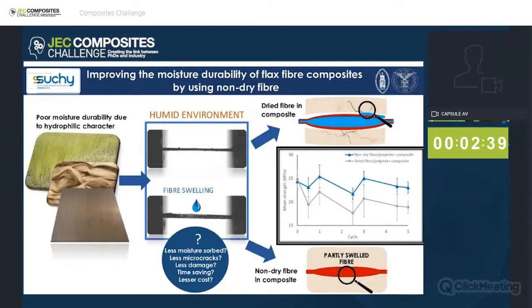additional advantages of using non-dry fiber could be lesser cost and time saving in the manufacturing of composites, since the process of oven drying the fiber is eliminated. So this simple idea inspired us to investigate the potential benefit of using non-dry fiber over the oven-dried fiber in composites. So in this research, we hypothesized that for composites made of non-dry fiber, which already contains some amount of moisture and is already partly swelled, the swelling and shrinking of the composite due to moisture absorption is reduced, thereby retaining the dimensional and mechanical properties of the composites over time.